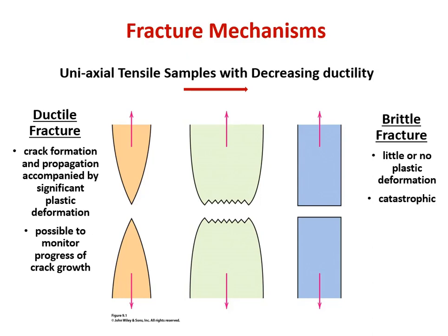A brittle material, on the other hand, will only deform elastically, with little or no plastic deformation, and then just snap. So it will retain almost the same exact cross section that it had to start with. And again, of course, all of its elastic deformation will be recovered when it fails. Most typical materials, most of your engineered metals, will be somewhere in between, shown in the central gray schematic, where you'll get some necking, some plastic deformation, but not as much as we would say maybe with a viscoelastic polymer.